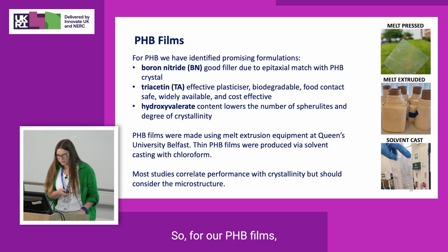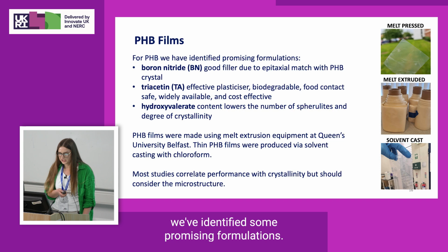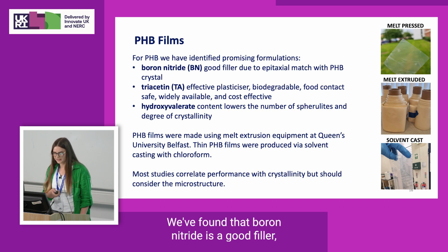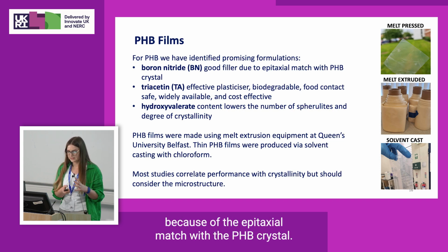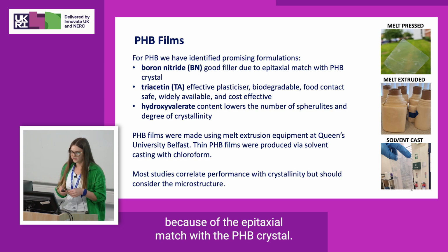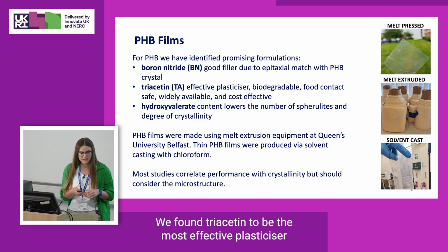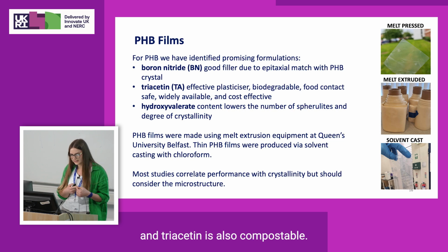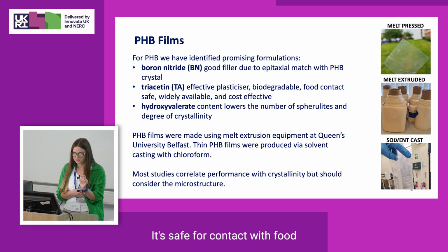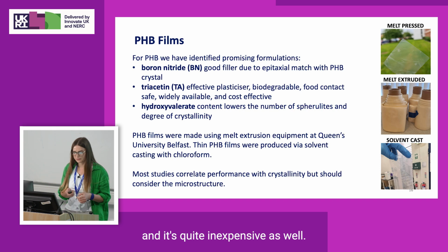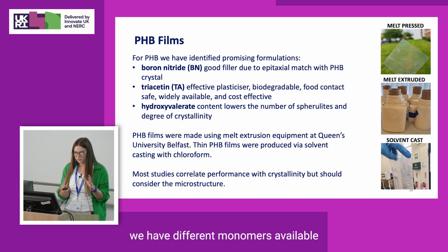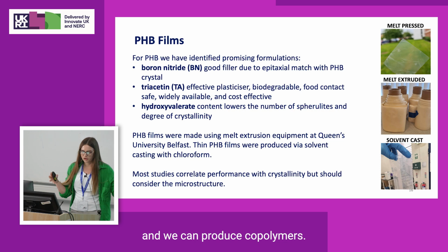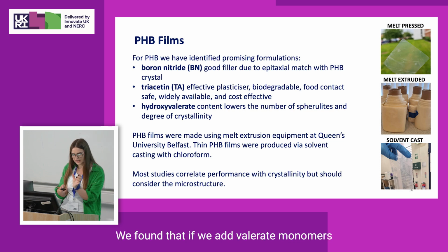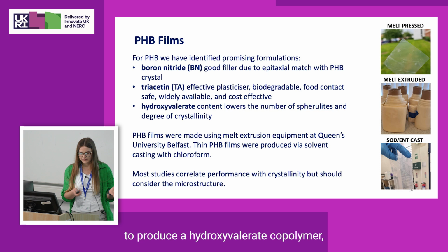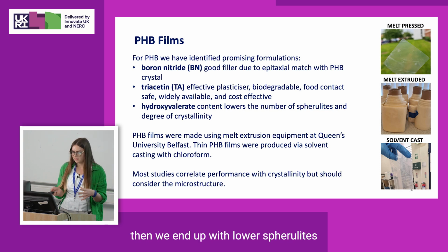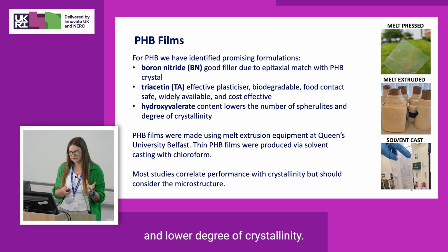So for our PHB films, we've identified some promising formulations. We've found that boron nitride is a good filler because of the epitaxial match with the PHB crystal. We found triacetin to be the most effective plasticizer that we've looked at. And triacetin is also compostable. It's safe for contact with food, and it's quite inexpensive as well. And I mentioned we have different monomers available, and we can produce copolymers. We found that if we add valerate monomers to produce a hydroxyvalerate copolymer, then we end up with lower spherulites and lower degree of crystallinity.